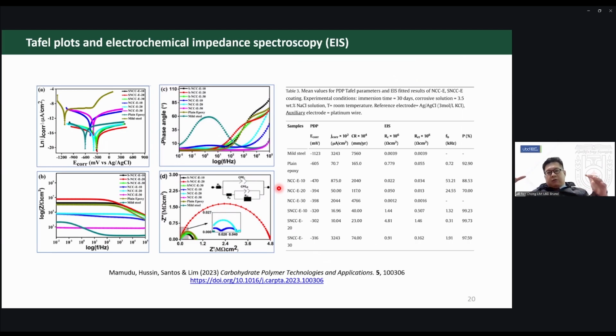Normally, with a barrier, you think of them like introducing a double layer capacitance. So with a double layer capacitor, normally you have time constants associated with it, and the different time constants that you get from fitting the equivalent electronic circuits to this Nyquist plot give you an idea of how the diffusion pathways are taking place for the corrosion. So if you have one time constant, you know there's only one electrochemical diffusion taking place.